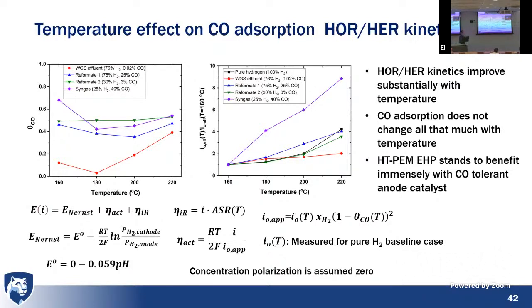And we tried to back out the adsorption coverage of CO on the electrocatalyst with this model, and we didn't see it change a whole lot with temperature. It was more of a function of the CO content in the gas stream. But if we look at the exchange current, right, how fast we're doing the HER kinetics, that was a strong function of temperature. So what this tells me is actually we do have an electrocatalyst that's CO tolerant, we would do better.